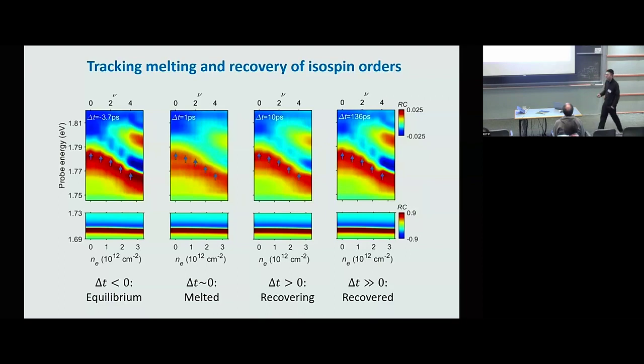Maybe along the same lines, you see a feature in label 4, which should just be the film back. That's not really an isospin. Yes. So what exactly are these peaks measuring? Okay, so these are measuring the polarizability of the graphene layer. So they will be affected by isospin orders. They're also affected by a big charge gap. So we will see both in this measurement.